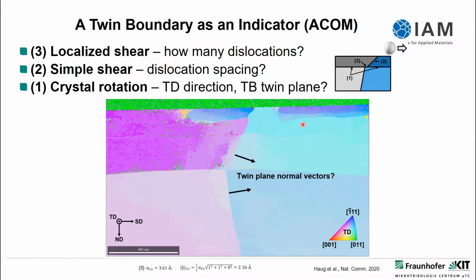And so that also makes sense, we actually see this. The other thing we wanted to see is, what about the twin plane? What about the twin? Do we destroy the twin in this process? Because if we stay in this picture of a deck of cards, we would really just shift the twin plane, not destroy it, just tilt it.